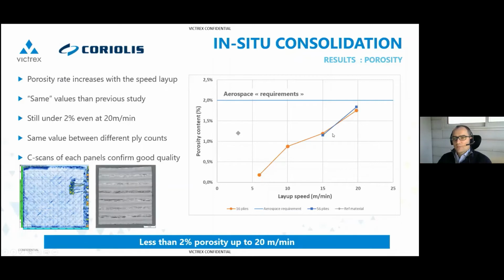As I mentioned, we tried a bunch of things, and also a thick panel. That's the blue curve here at 56 plies, for instance, instead of 16 plies. And it was also, by the way, a quasi-isotropic composite laminate. So the good news is that the thickness does not influence the porosity results. Even for a thick panel, we were more or less within the same range, and that's thanks to the in-situ process.